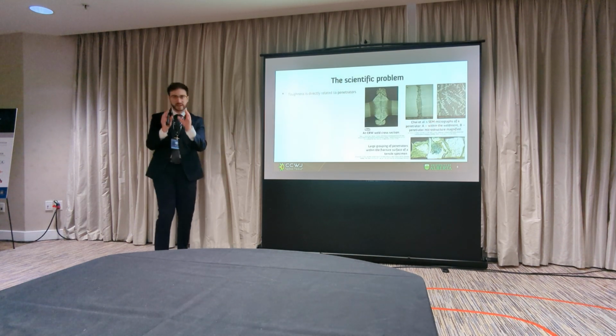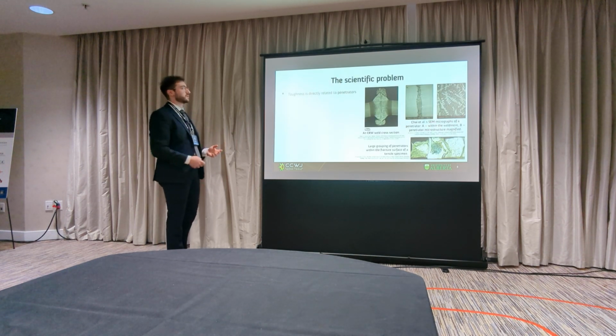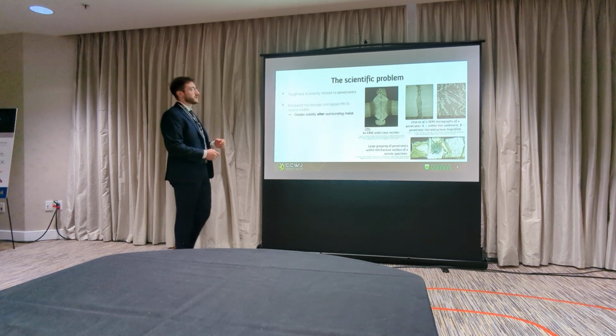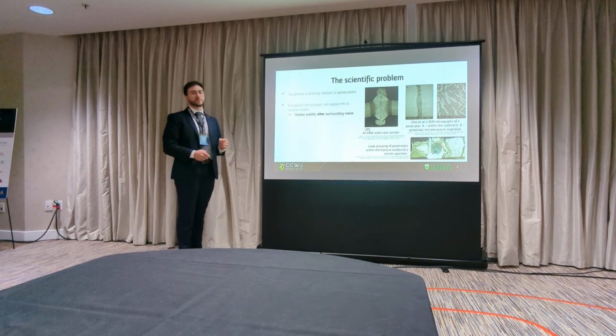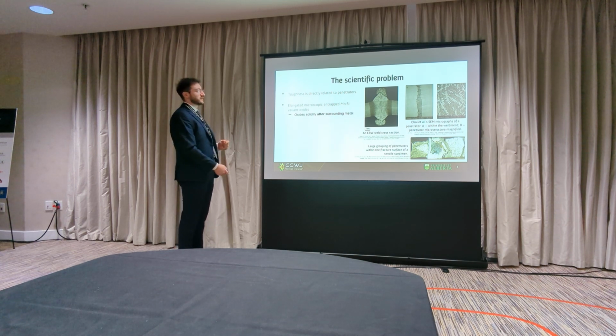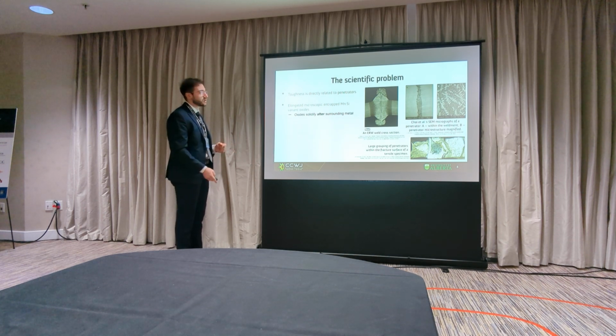So the actual scientific problem in my thesis: the penetrators themselves. Toughness in ERW components has been known for 40 years to be directly related to penetrators. What are penetrators? They're elongated, microscopic, trapped oxides, usually the manganese silicon variant. And the key thing about them is that they are evenly distributed along the bond plane of an ERW weld. So this is a cross section of an ERW weld. The pipe is running in and out of the page.